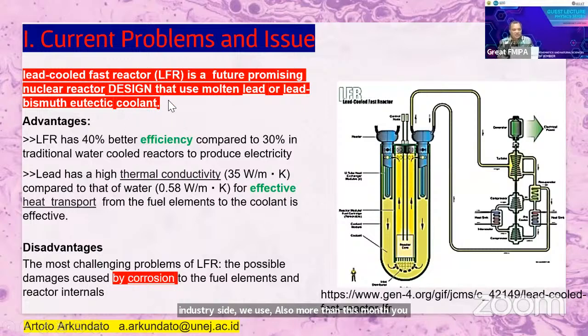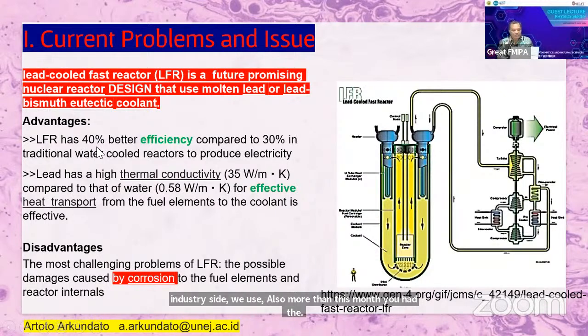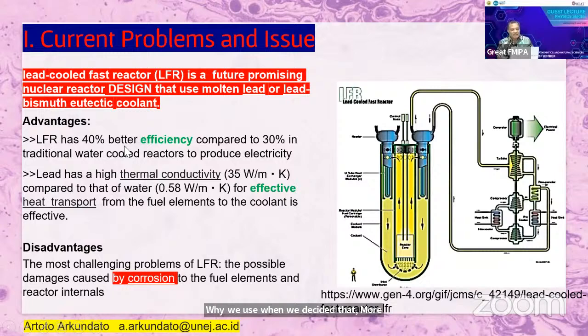Why do we design this LFR? Because it has better efficiency, more than 40%, compared to 30% in the traditional reactor, the current reactor. And also lead has a high thermal conductivity compared to water, which is used in traditional reactors. So lead is effective for heat transport from the fuel element to the coolant.